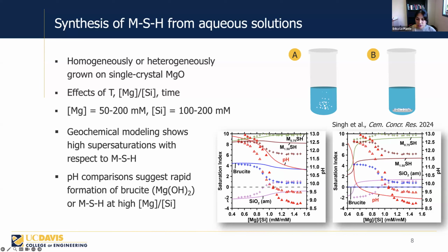So this shows the saturation index as a function of the magnesium to silicon ratio of the solution. Saturation index gives the logarithm of the ratio of the ion activity products and the solubility products. That means that positive values of saturation index mean that there's a tendency for precipitation, and negative values of saturation index mean a tendency for dissolution. We can see here in the models that there are high degrees of supersaturation with respect to MSH in all cases. The symbols here represent the measured values.